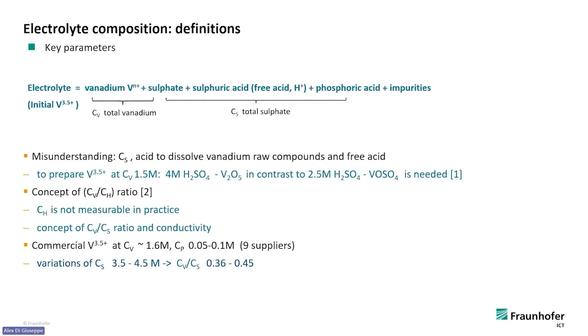So first of all, we defined key parameters for the composition. The problem is that we know that if you have free acid, so hydronium ions, as a chemist would say, in the electrolyte, you would have a higher stability. But the problem is you cannot measure the acid content. You cannot measure the pH. You cannot put a pH electrode in such an electrolyte. It's much too concentrated, and you would get a wrong reading if you use a pH meter. So the free acid content is an unknown.